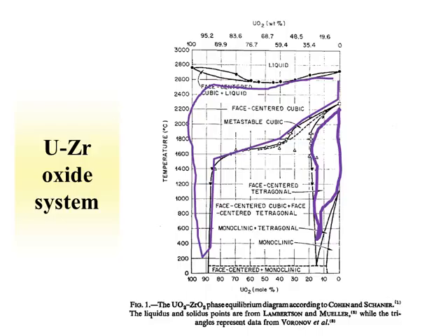An example of the uranium-zirconium oxide system is shown here. This is the phase diagram showing temperature plotted against the percent by mole of UO2. 100% UO2, 0% UO2. So you would imagine a nuclear fuel. You would be somewhere in this regime. We'd have solid solutions in areas that are marked by the purple.